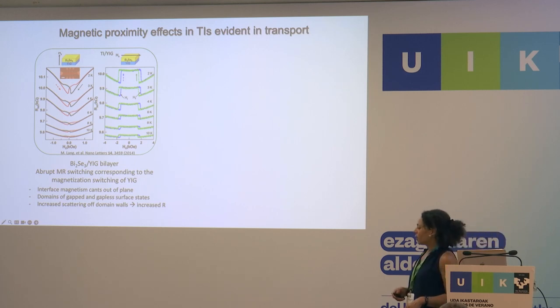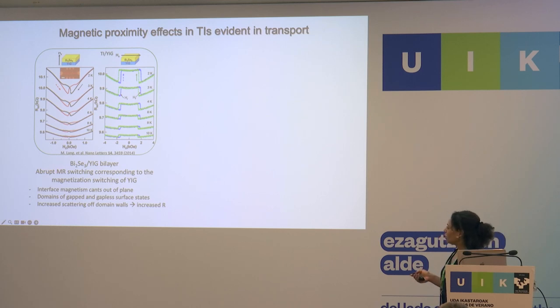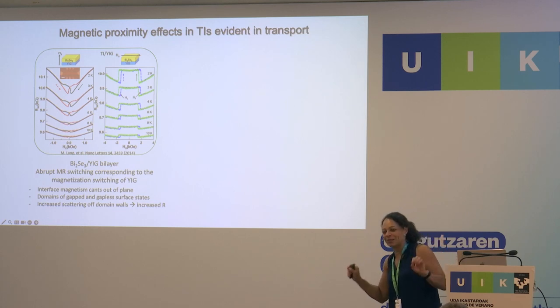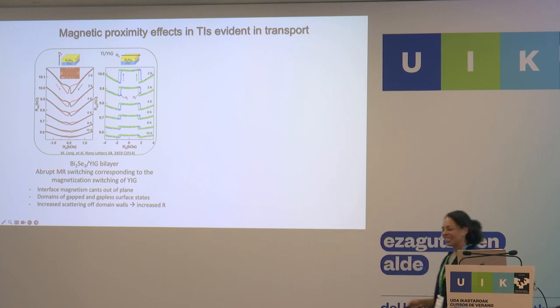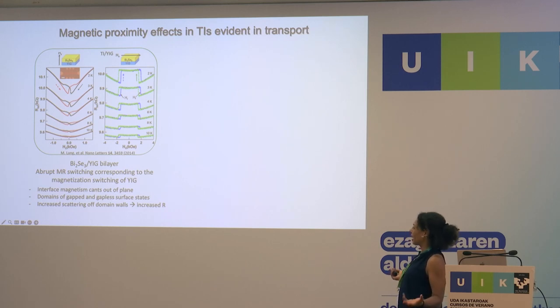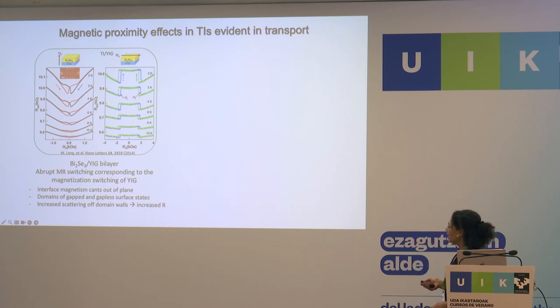I come from a superconducting background, so it's always funny to me that in magnetism, all you ever look for is hysteresis. Doesn't matter what you want to get. As long as you see hysteresis, you know it's a magnetic effect, and you send it out there. So in this case, these are hysteretic, so they're due to the magnetism. But the origin of these features is just not well characterized or well known. In this paper, they said that this switching corresponds to switching of the underlying magnet, so there is a proximity effect. The magnetism cants out of plane, is what they guessed, and you have domains of different states.